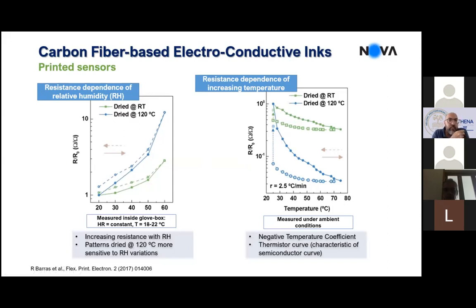So you can still separate the contribution of temperature by proper training of the algorithms that you use then to make the readings. And of course, you can then decouple the response of the humidity and temperature, because the response to humidity comes mainly from the CMC that exists in the printing pattern, and the response to temperature comes from the carbon fibers.